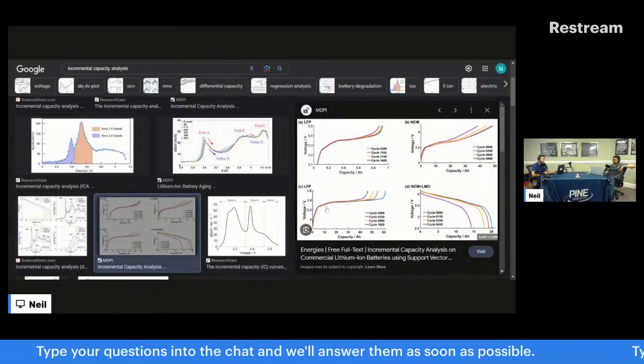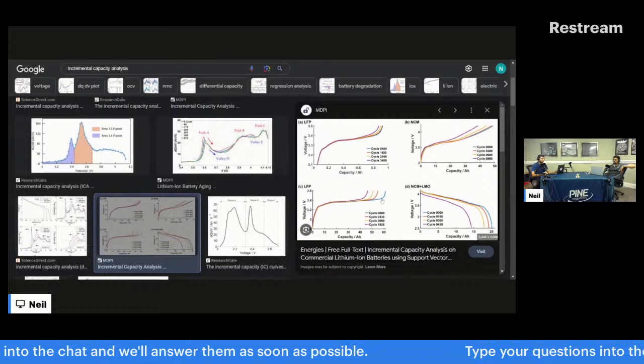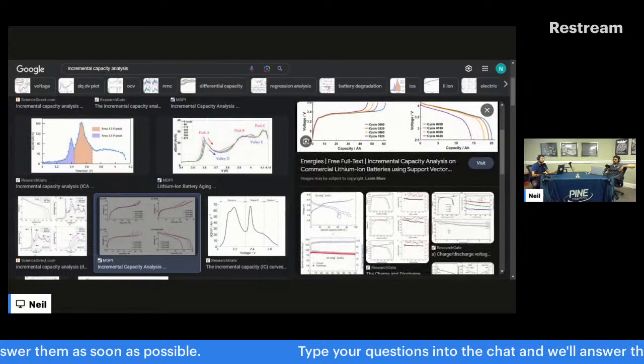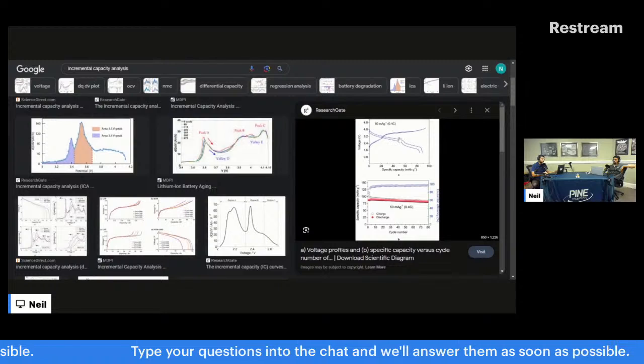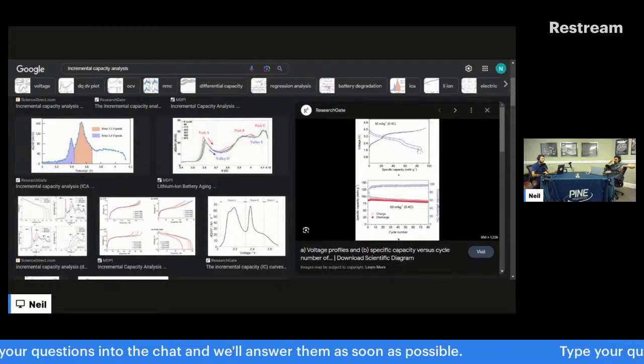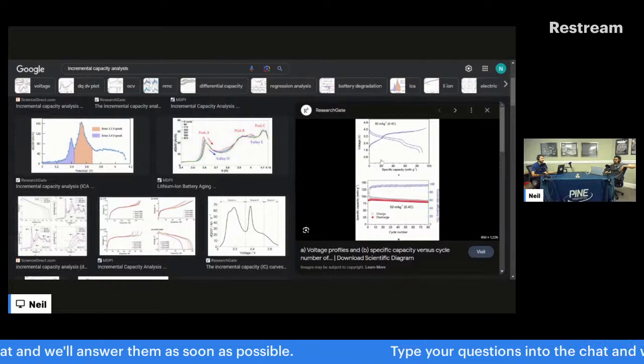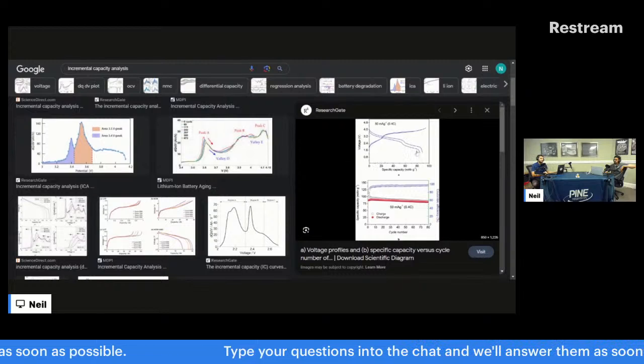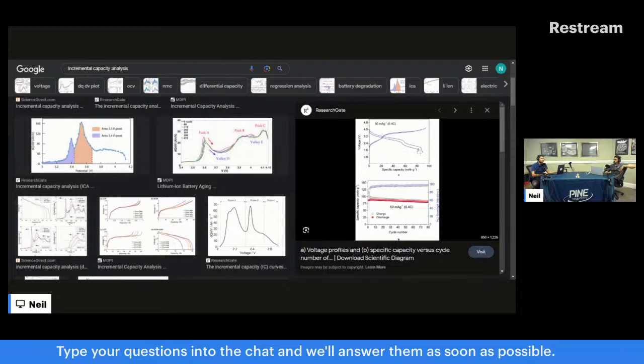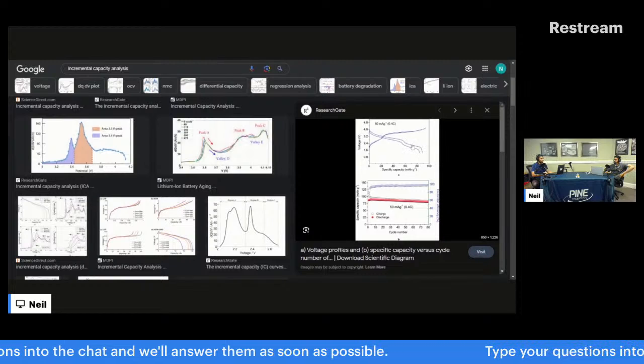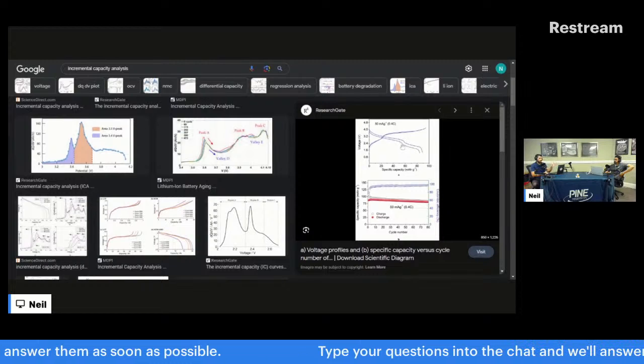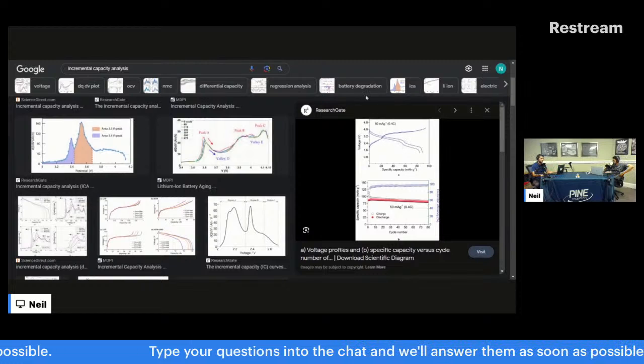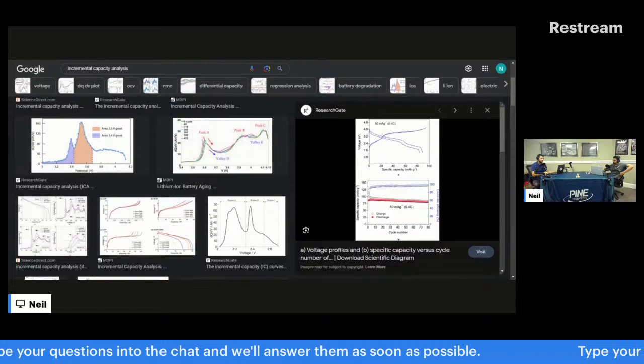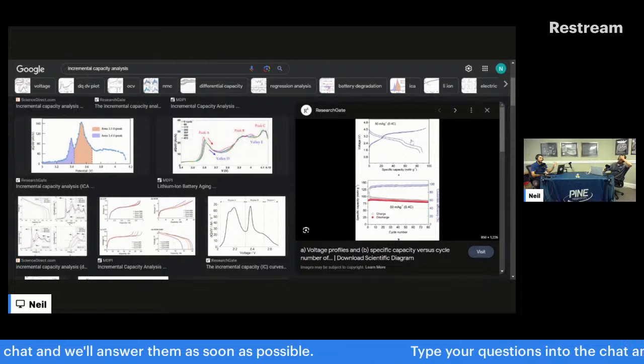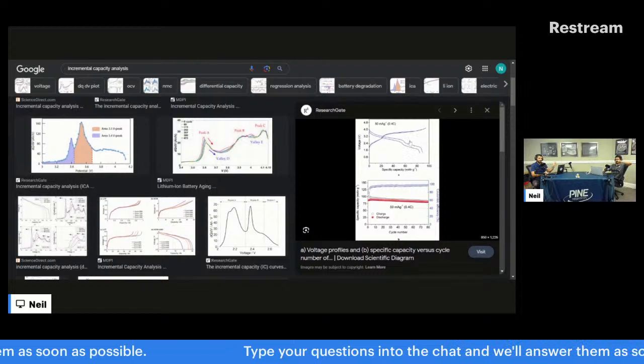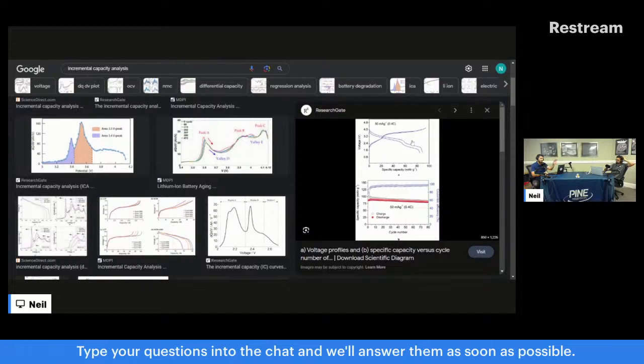Sometimes this is just whatever this material happens to be that I found in a Google search. But sometimes you'll have something like two flat levels. So what you might have is that the second peak being larger just means that the second charge or discharge process is longer, is contributing more. You might be overcharging or over-discharging, ripping the electrolyte apart and making more SEI. The SEI could be getting thicker. That's one reason why you have an extended charge-discharge profile.